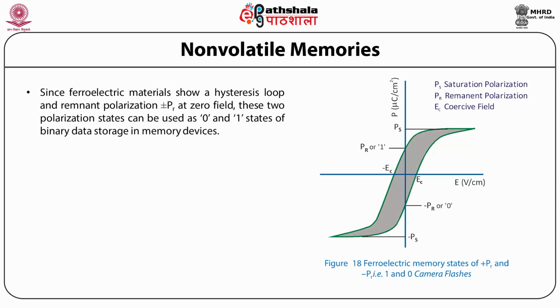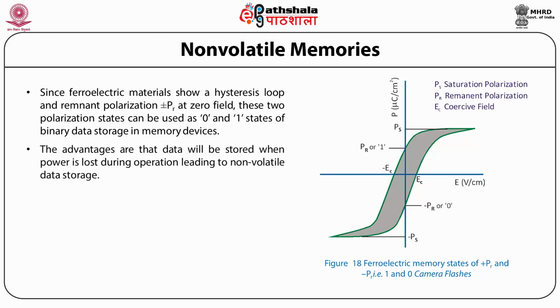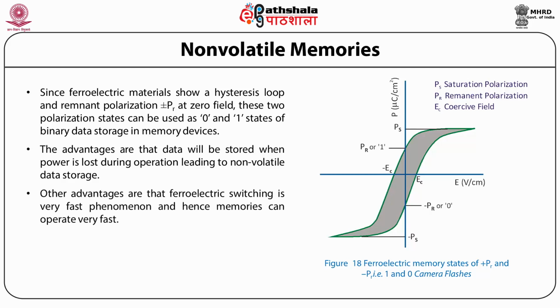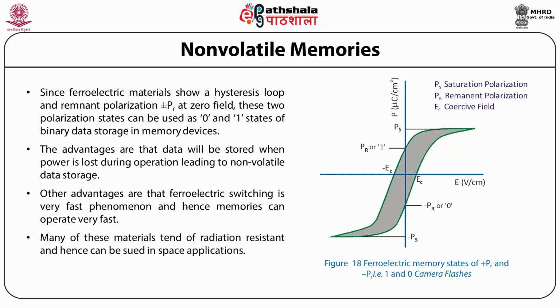Since ferroelectric materials show a hysteresis loop and a remnant polarization at zero field, these two polarization states can be used as 0 and 1, corresponding to plus PR and minus PR states of binary data storage in memory devices. So such states you can see in the plot shown in the slide, where the ferroelectric memory states of plus PR and minus PR are shown. The advantages are that the data will be stored when power is lost during operation, leading to non-volatile data storage. Other advantages are that ferroelectric switching is a very fast phenomenon and hence memories can operate very fast. Many of these materials tend to resist radiation and hence can be used in space applications.